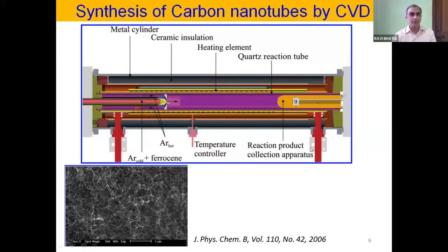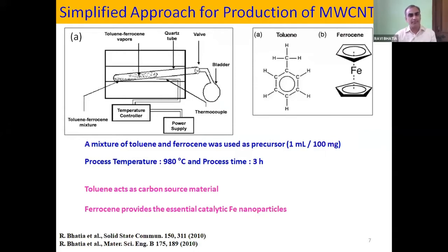So we chose to replace this method while doing the experimentation with the production of carbon nanotube in our lab. We made it very simple. We just need to have a furnace here, which is capable of reaching 900 to 1000 degrees C, and we require a quartz tube which can be connected to a bladder and valve which collects all the gases after the reaction. So it is a very simple method which can be utilized for the mass production of multi-wall carbon nanotubes. Here we have used a toluene and ferrocene mixture, and after optimizing a few times, you can get very high quality carbon nanotubes from this particular setup. And this setup was hardly 20,000 rupees when it was first built in our lab. That was in 2008, and we produced two papers out of this on the synthesis.